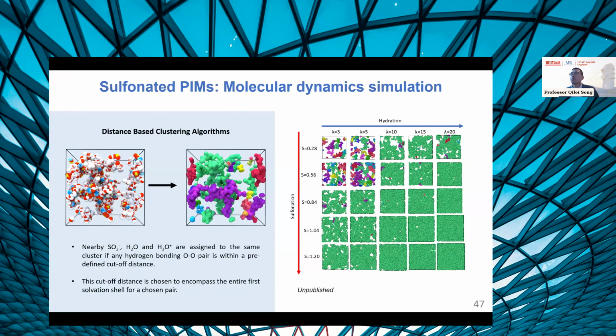So we actually were able to simulate the different degrees of sulfonation and also the hydration level. You can see that if you got a high degree of sulfonation and a high degree of hydration, the water clusters become connected. You got a fully connected water channel. So the trick is how can we tune the degree of sulfonation and limit the hydration.